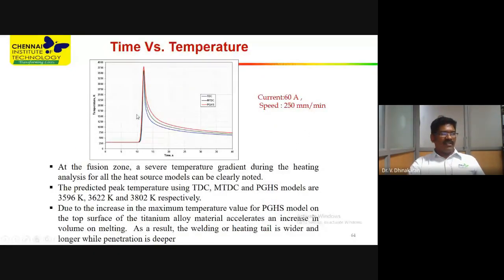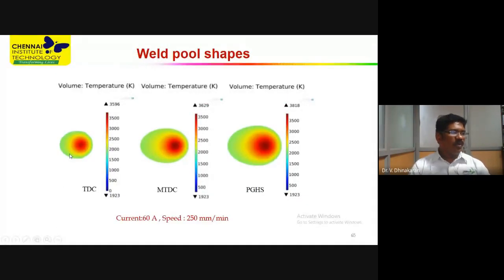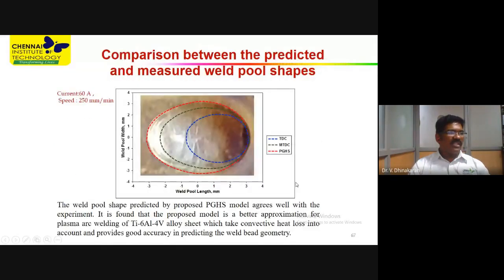Okay, and this is the peak temperature measured by using these three heat source models, and it is found that Dinakaran's model is correctly predicting the temperature. Okay, so this is the welding pool predicted by the three different heat source models, and this is the physical welding pool from the experiments, and the physical welding pool measured from the experiment is correctly predicted by Dinakaran's model.